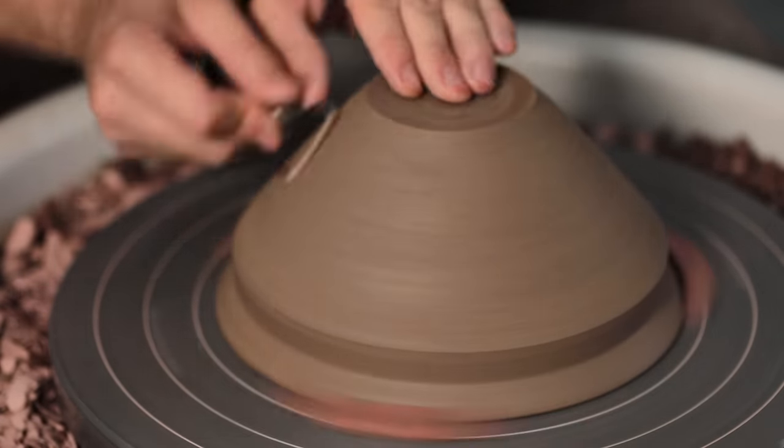And it's also for a similar reason that I always begin by cleaning the white pots, as the white simply can't contaminate the pale green or the dark green, as they all share the same base recipe. But the pale green glaze and the dark green glaze can contaminate the white, as they contain red iron oxide that the white doesn't.